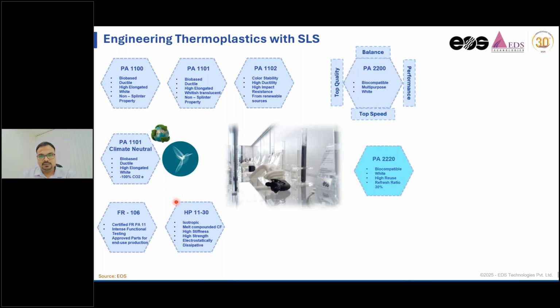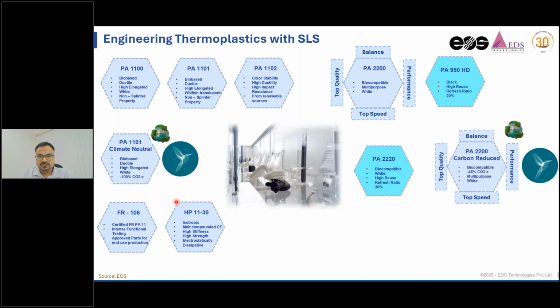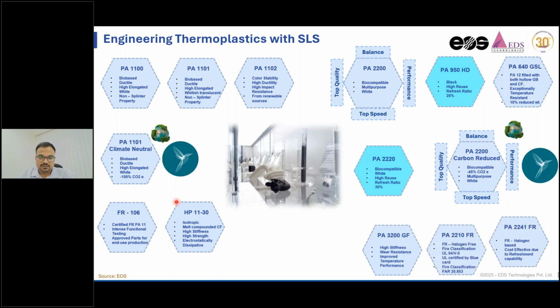In nylon 12, we have highly reusable PA2220. If you remember, the refreshing ratio I was discussing, in this material we are able to reclaim 70% of the powder from the previous cycle. And in a material called PA950 HD, we are able to reclaim 80% of the powder from the previous cycle. Today, this makes it more economic and adds more reusability to the process, making it more sustainable as a production technology. We have PA640 GSL, which is 10% lighter than normal nylon material, used for lightweight applications, and it's a carbon-filled composite material. We have glass filled material and other flame retardant material, nylon 12 FR, which is used for flame retardancy.